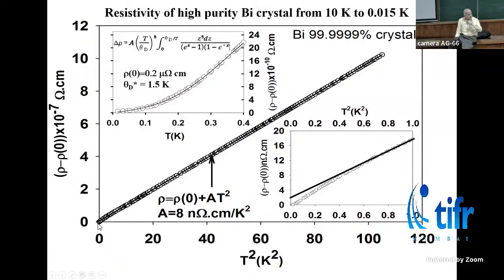It is not very clear, and you can crazily fit this to a Bloch-Grüneisen theory. But don't believe that theory. It is just what I showed you. Something else is happening. The T⁵ is not coming because of Bloch-Grüneisen. We need to look at the Hall measurements at such low temperatures. This is something I don't have the energy and time for, but there is definitely a change in the electronic structure, and that is how I think bismuth is superconducting at 0.5 millikelvin. The reasons are not very clear.